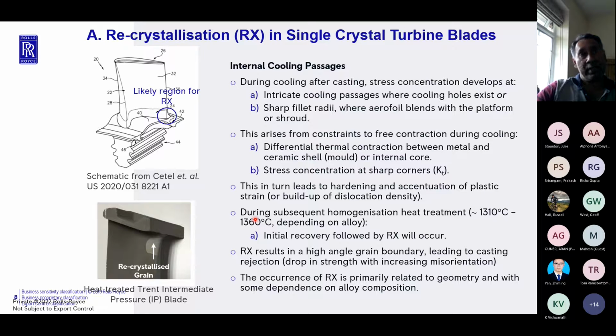So what happens is when you have a pre-existing plastic strain beyond a certain value, which is equivalent to a certain dislocation density, you've got high strain energy within these regions. And during homogenization at these temperatures, which is done primarily to remove the segregation, another effect happens. You have recovery followed by recrystallization. So while on the one hand you're trying to homogenize the microstructure to get a segregation-free casting, at the same time, in regions where you've got high plastic strain, you're producing recrystallization.